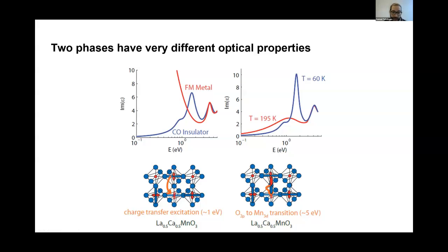So this is an excitation which takes an electron from a manganese 3 ion and transfers it to an empty manganese 4 site. So at this point, it's good to mention that this insulating state is what's called a charge and orbitally ordered state, which essentially means that the oxidation state of every manganese alternates in the unit cell. And for the manganese 3s, they have a Jahn-Teller distortion and they have a particular EG orbital polarization. And this EG orbital polarization also alternates. So you get this sort of double checkerboard pattern where, imagine a checkerboard where all of your black squares are manganese 4s, all your white squares are manganese 3, and then every other manganese 3 has an alternating orbital polarization.